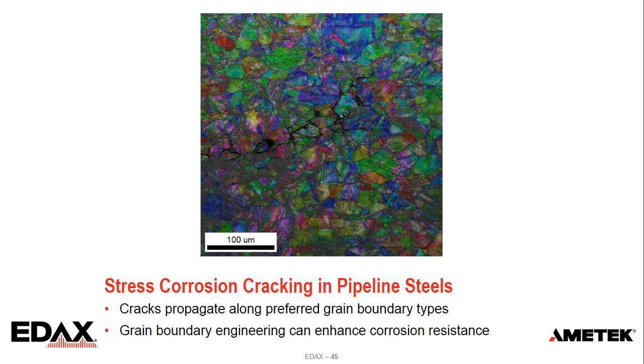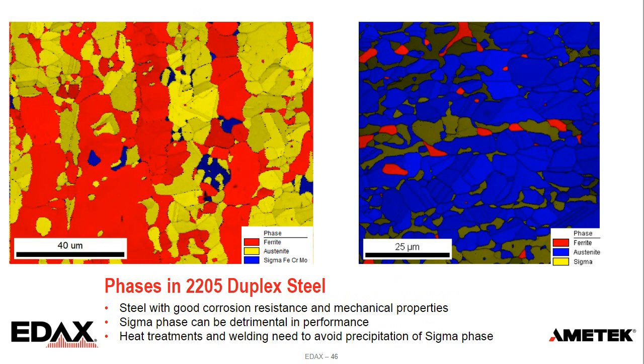I want to talk a little bit about looking at different phases in steel. It's generally easy to think of steel as a single or dual phase steel. Oftentimes there's lots of other stuff going on in there. I was talking about pipeline steel. This is a 2205 duplex steel used for its good corrosion resistance and mechanical properties. But if it has a sigma phase, it can be detrimental to this performance. So when they heat treat and weld the sample, they try to control the conditions to avoid precipitation of the sigma phase. These are two different examples of the 2205 that were heat treated a couple of different ways to measure the amount of sigma that was present.